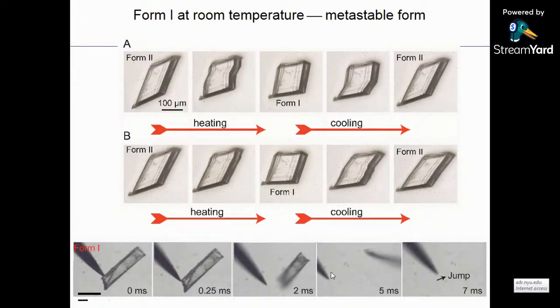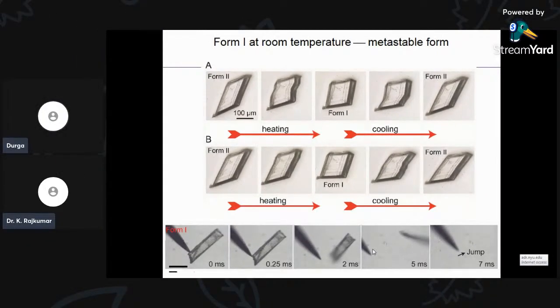You can do several cycles, but after a few cycles, these form 1 crystals at high temperature, when we are cooling to room temperature, should be converted to form 2 crystals, but they don't convert. So they remain as form 1 crystals at room temperature. These crystals are known for their metastability. That means when you touch these form 1 crystals at room temperature, they spontaneously jump. We named this mechanosalient behavior.